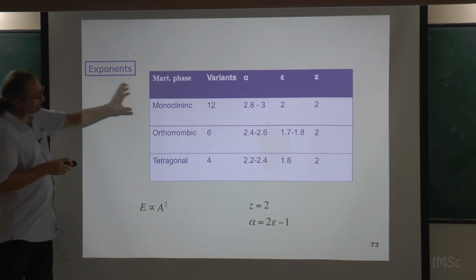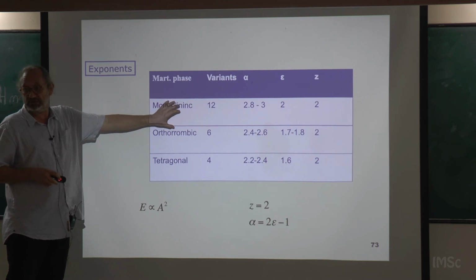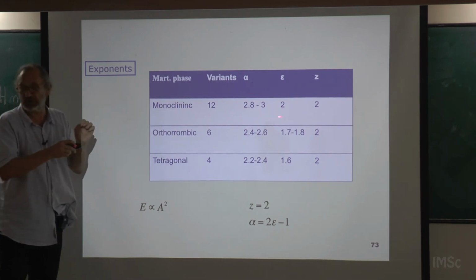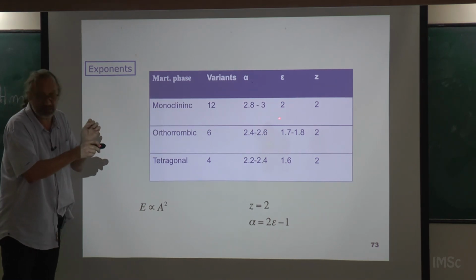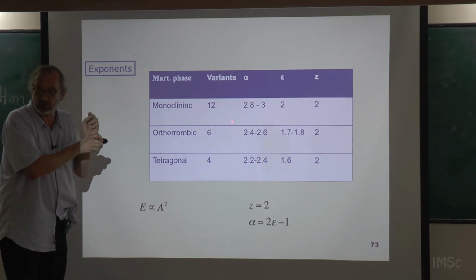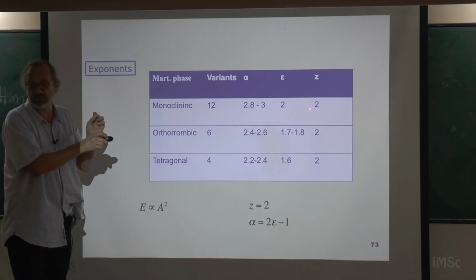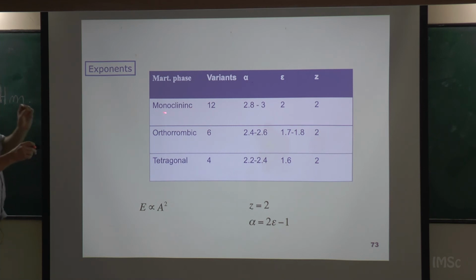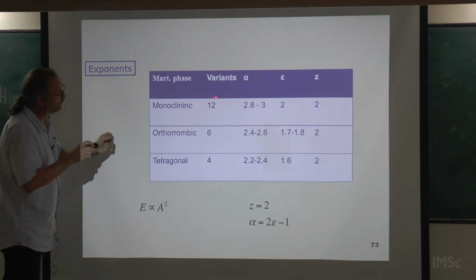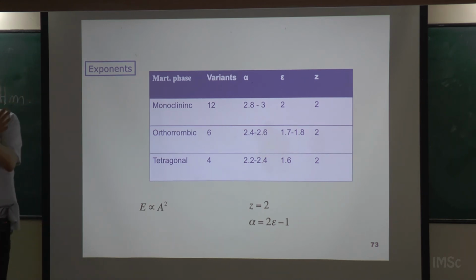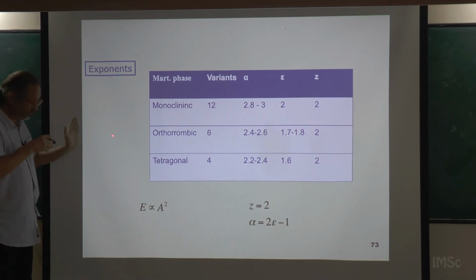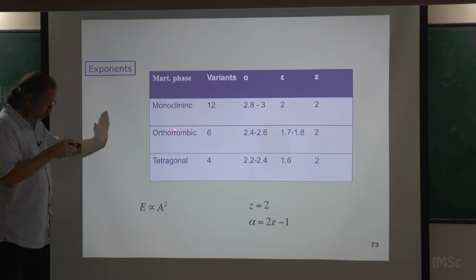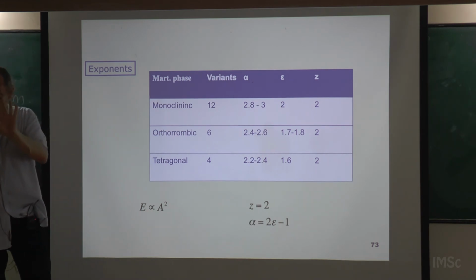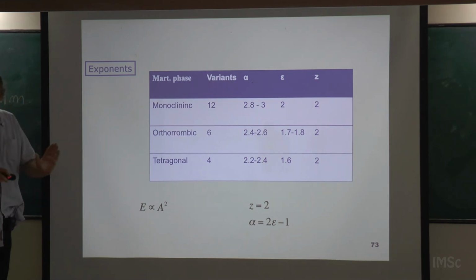all the alloys that transform to the same low symmetry structure have the same exponent for the amplitudes and for the energies. This is the exponent for the distribution of amplitudes. This is the exponent for the distribution of energy. Not only that, when we have a transformation from cubic to monoclinic, we know that there are 12 equivalent variants. When we go from cubic to orthorhombic, we know that there are 6 equivalent variants, and when we go to tetragonal, we know that there are 4 equivalent variants. Okay?